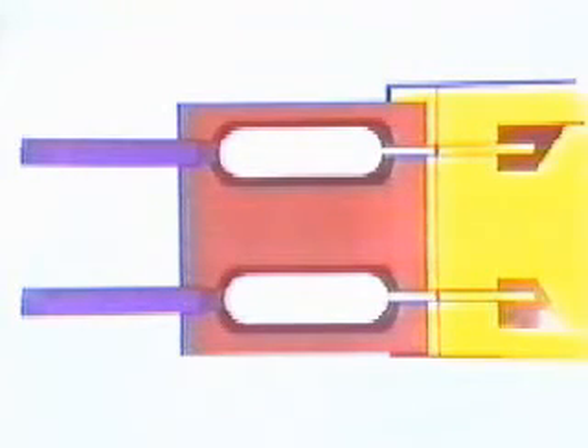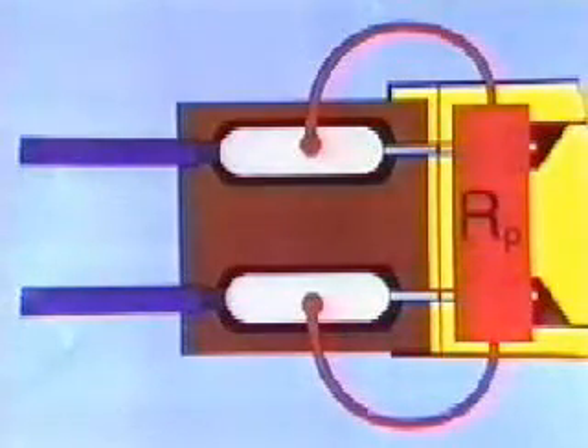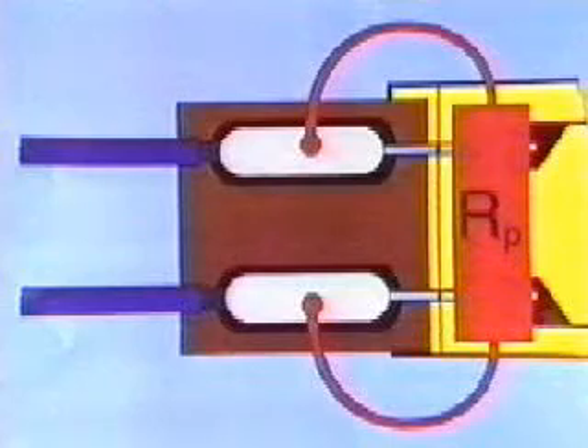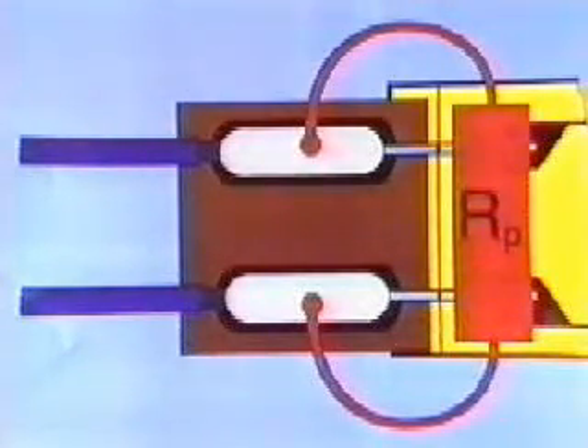It's easy to measure the insulation resistance between the strain gauge and the test object, but it's impossible to measure it between the two soldered joints. Only the resistance of the measuring grid can be measured there. But the insulation resistance forms a shunt to the strain gauge resistance. If its value varies, then the resulting resistance of the parallel circuit also varies, causing zero-point fluctuations, which may be erroneously blamed on the strain gauge. Any colophonium residues can only be found by a visual check.